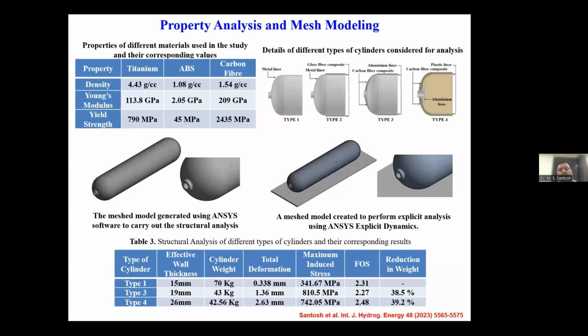So in principle, if you are looking at a cylinder which can hold hydrogen under high pressures of 350 bar, 350 into 2.48 times has to be the actual testing parameter, or the pressure at which the cylinder has to be actually tested, and that will give us whether the cylinder can bear the required pressures at that level. And if it passes that, then there's nothing beyond that, and the material will automatically qualify to be used as a type 4 cylinder.